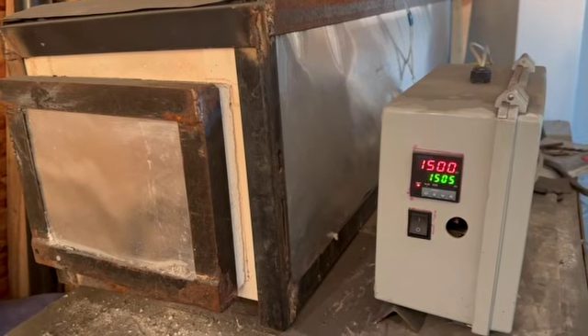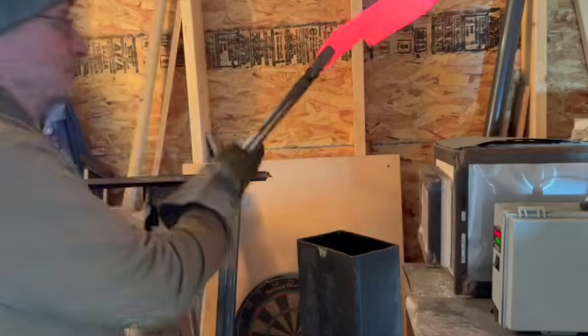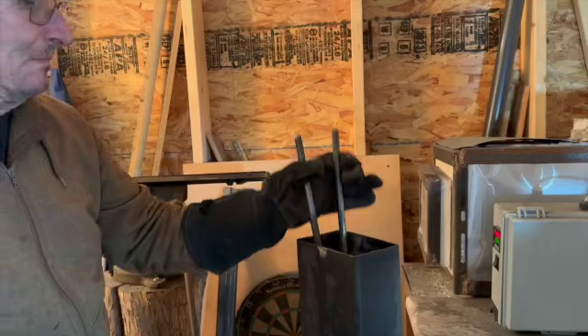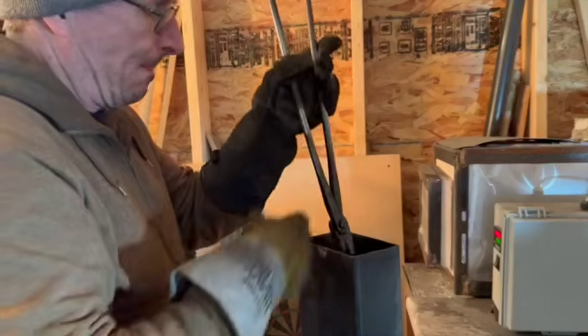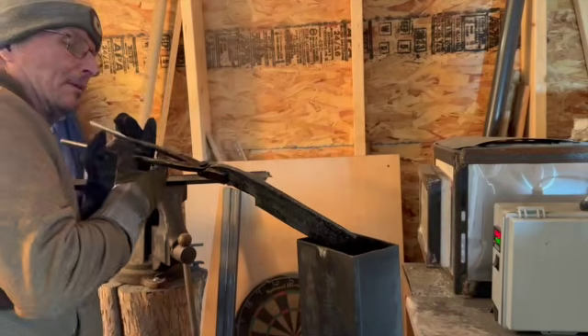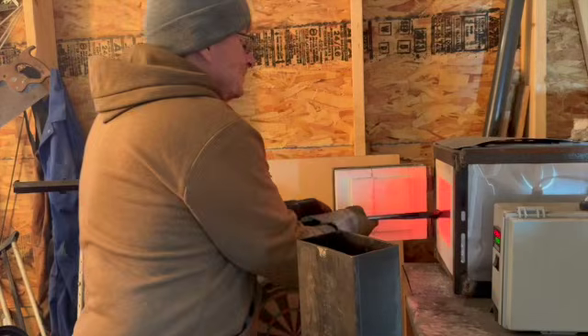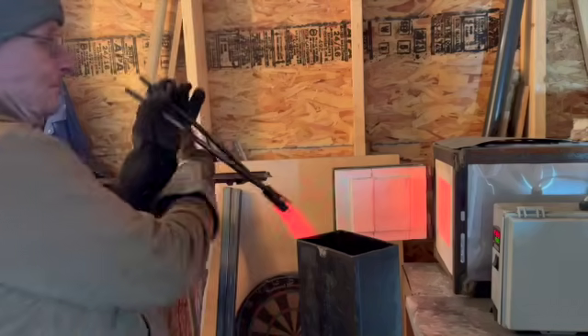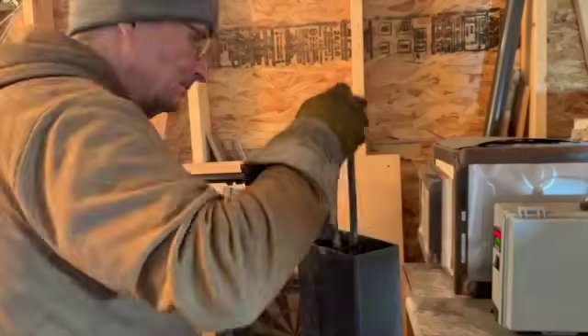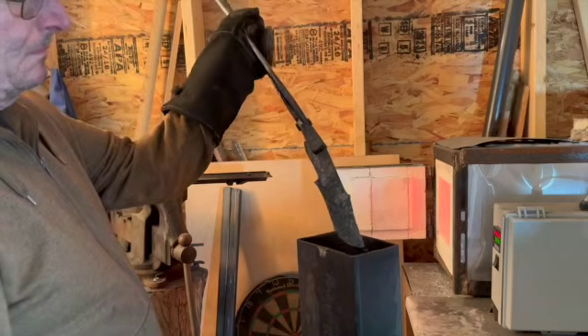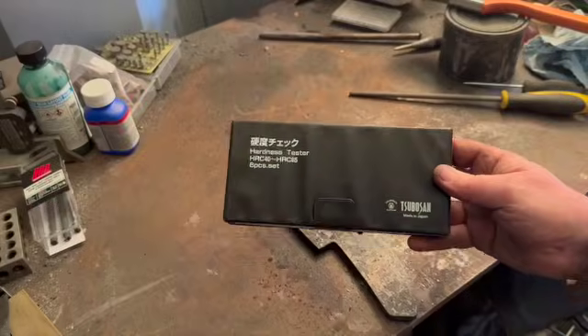I'm using Parks 50 to quench these. We're putting them in at about 1500 degrees, soaking them for about 30 seconds. And the first one comes out nice and straight. And the second one's good too. No pings, no cracks, no warps. I like it. We'll check the hardness just to make sure our quench worked.